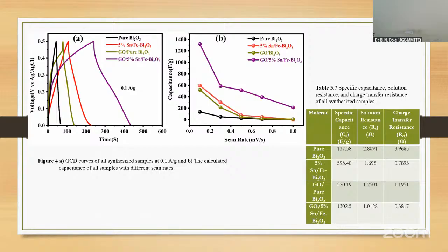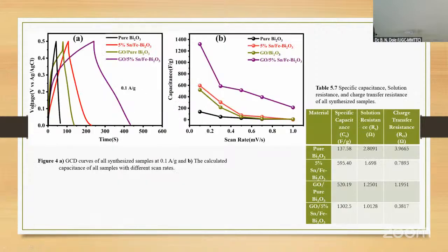This is the galvanostatic charge discharge curve, and see that one, the galvanostatic charge discharge curve of all synthesized samples at 0.1 ampere per gram, and the calculated capacitance of all samples with different scan rates. Okay, this is the voltage and this is the time. Scan rate.